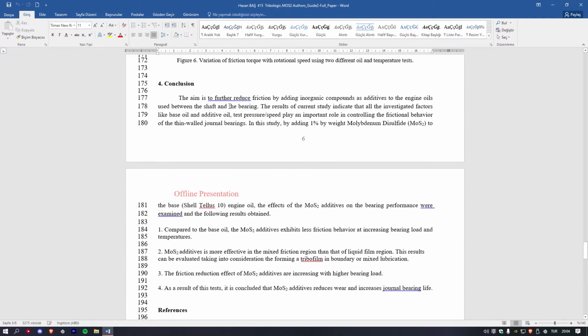Conclusions. The aim of this study is to further reduce the friction by adding inorganic compounds as additives to the engine oils used between the shaft and bearings. The results of the current study indicate that all the investigated factors like base oil and the additive oil, test pressure, and test speed play an important role in controlling the friction behavior of the thin-walled journal bearings. In this study, by adding 1% by weight molybdenum disulfide to the base oil Shell-Tellus 10 engine oil, the effect of molybdenum disulfide additives on the bearing performance was examined and the following results were obtained.